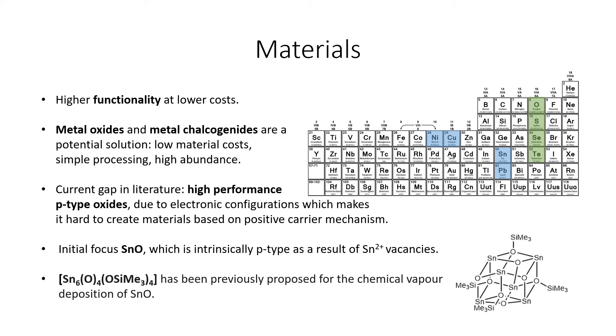There is currently a lack of available high performance p-type oxide materials, and being able to access these would significantly increase applications. The initial focus will be on the deposition of tin monoxide, which is p-type as a result of tin(II) vacancies.